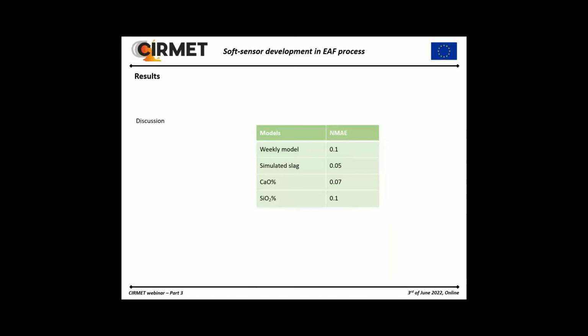And finally, we are going to compare all the models that we obtained. So the problem of predicting the quantity of the slag was quite challenging, because the data was not reliable at all, because some slag was always remaining in the furnace, and also because of the complexity of the process itself. So here you've got the normalized MAE values for all the methods.